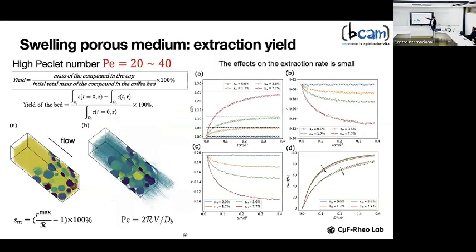Okay, good. So we made some simulations. We take a toy 3D model reproducing the porosity of a typical coffee bed. And now we look at the yield. Remember, the yield is the mass which has actually been extracted. It's not the concentration, which would be the strength. This is the overall mass which has been extracted. You can see the swelling, here we show results for different degrees of swelling, from no swelling to 7%. If we increase the swelling, essentially the entire volume will expand, the volume of the simulation will expand up to, let's say, 7%. Porosity will decrease. This will produce a decrease in the overall flow rate, because obviously the solid volume fraction increases, the porosity decreases, and also the flow rate will decrease.